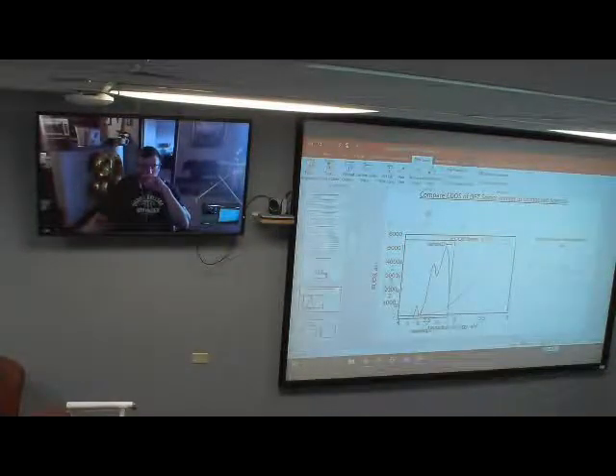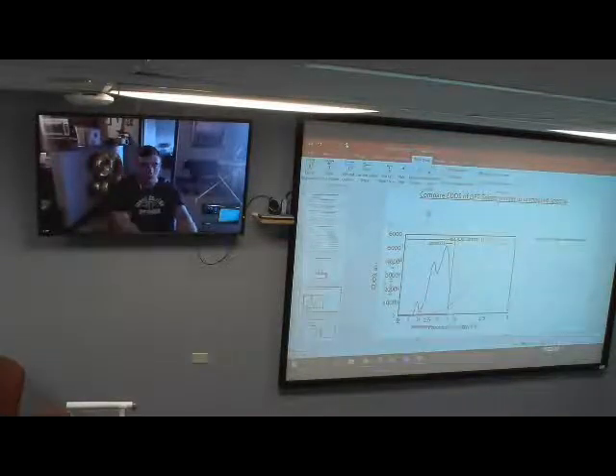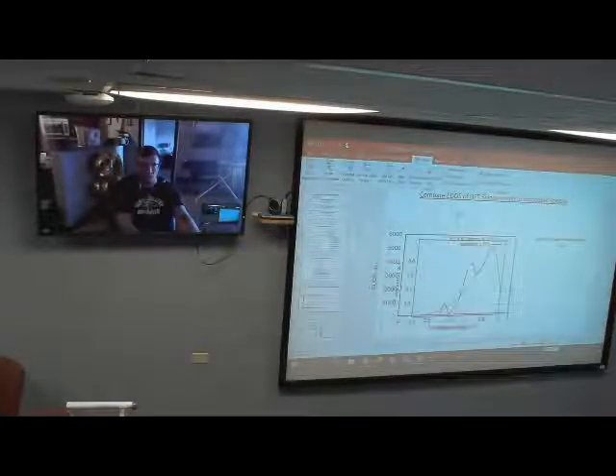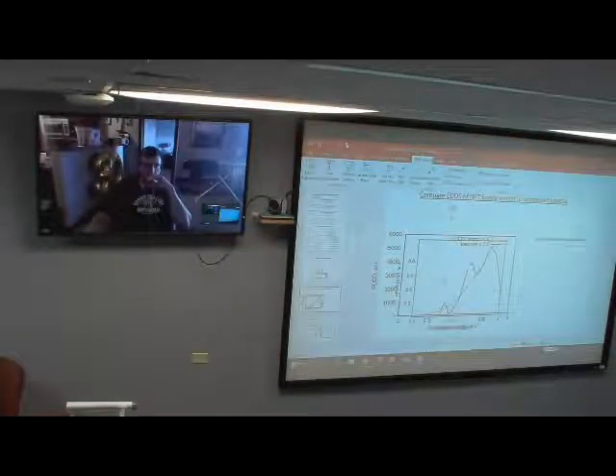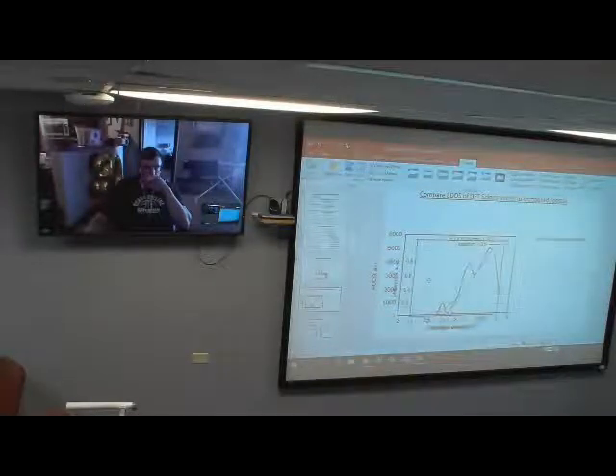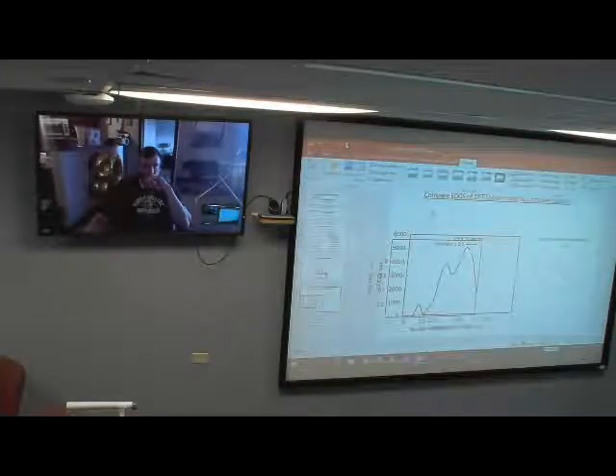So that's the red curve, and you put it on top of just all possible transitions, right? Yes, so just counting all possible transitions. And for all possible transitions, you already don't have such a discrete spectra as for the particle in the box, right? Right. So you see the lowest transition only has a couple of counts, and the higher in energy you go, the more states that you have. But interestingly, after you calculate the transition dipoles, do those peaks correlate with those features in your all possible states from particle in the box?